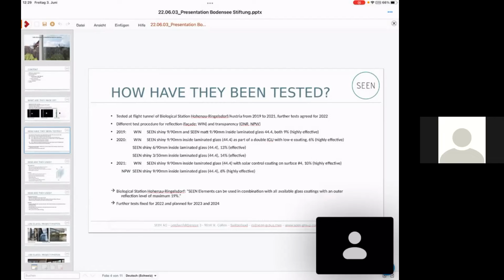So we used a pattern with 9 millimeter dots and 90 millimeter space from center dot to center dot inside the laminated glass. So we had both sides of 4 millimeter glass and 1.52 millimeter lamination foil in between. Both glasses reached a result of 9%, which means 9% of the birds flew towards the test glass and 91% flew against the not marked opposite glass.